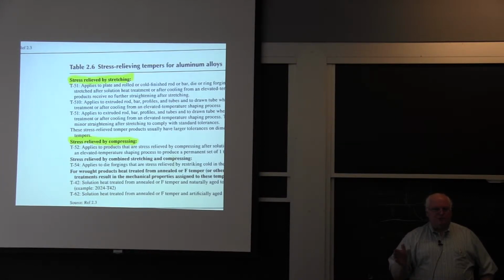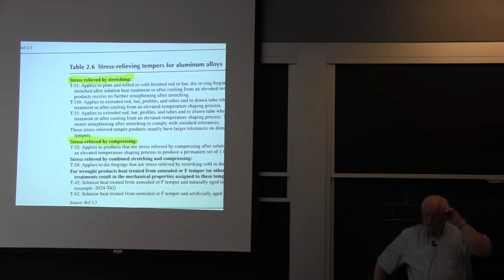stress corrosion cracks. We measured the residual stress by cutting that hole and measuring the thing very precisely before and after, and seeing how much the hole opened to expand. We estimated the residual stress of that at 8 KSI. That particular alloy, which was 6061 alloy, in the T6 optimum strength condition, has a stress corrosion cracking toughness of 5 KSI, which means 8 KSI residual stress, marine atmosphere, 5 KSI susceptibility, and we're right there in the middle of that little Venn diagram. And they would crack on the shelf without ever having been put in service.